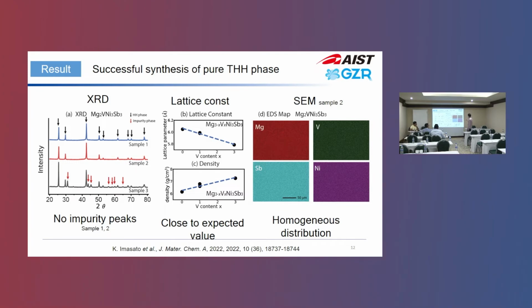And the SEM with EDS map is pretty clean. Sometimes with just ternary Half-Heusler compounds it is difficult to get the pure phase, but I think this is homogeneous enough. It is a low magnification picture, but if you look closer, I don't see many problems of impurities or secondary phases.